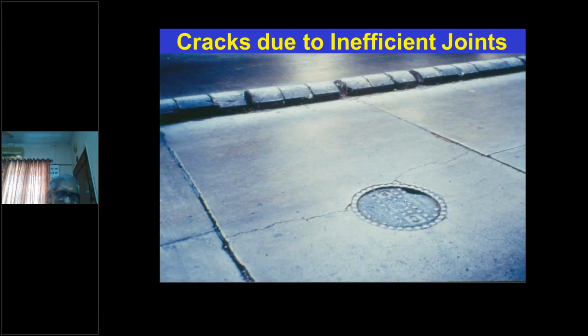If there is a manhole in between, the engineer tried to avoid making a joint. And here you can clearly see the concrete, being more intelligent than the engineer, has made a joint of its own. But this joint doesn't look very good, may not last, and is likely to have potholes later on with repeated usage. So one has to have a joint, and the panels should be reasonably square. You can see here, concrete has made a square panel by itself, not the rectangular one which the engineer made.